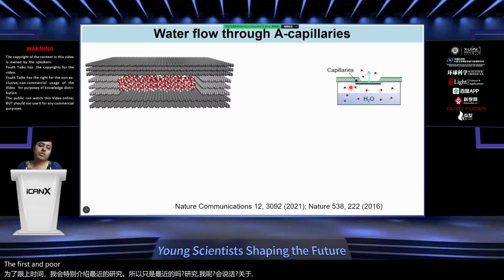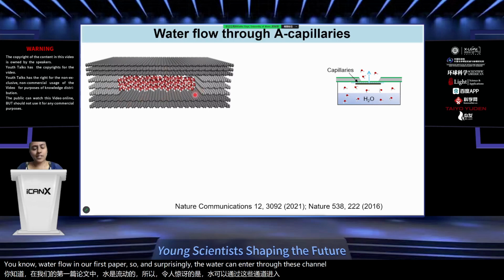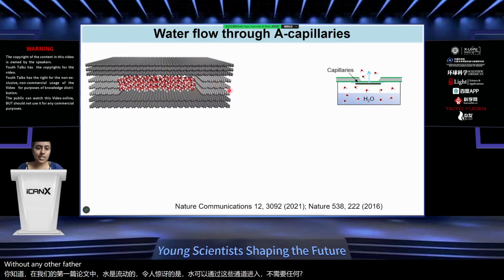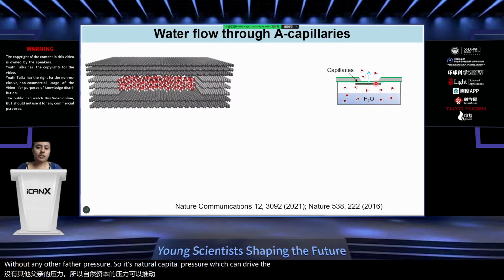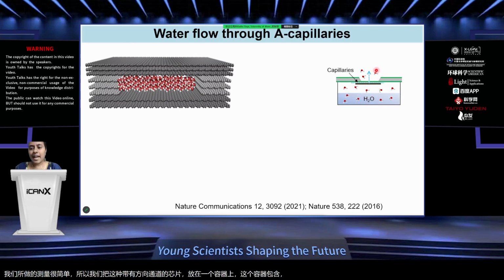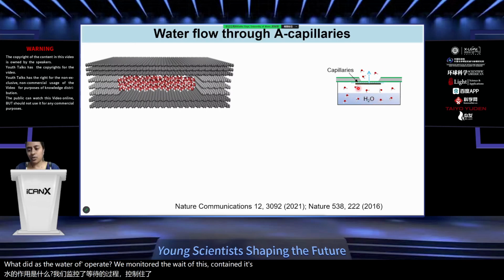The first and foremost study that we had done, because to our surprise, we initially thought even nothing would flow into these kind of tiny channels. So when we tested water flow in our first paper, surprisingly, the water can enter through these channels without any further pressure. So it's natural capillary pressure which can drive the water through these capillaries. And the measurement that we had done was quite simple. We put this chip with the angstrom channels on a container which contains water, and as the water evaporates, we monitor the weight of this container. So it's micrograms loss, and that can give us the estimate of water flow.